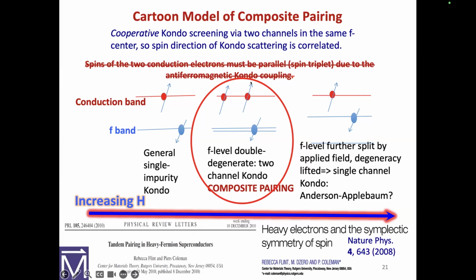And that scattering of those 2 separate electrons off that doubly degenerate f level, if you apply a field and split the Kramers doublet, it'll split linearly with field. So the idea is that as long as you have any pairing at all, you're going to get that linear splitting. If you do this at higher temperature, when you don't have those correlations, then you're not going to see a linear splitting. So this is an argument where we see something below TC and maybe something above TC that carries that. I'd love to talk about this more.